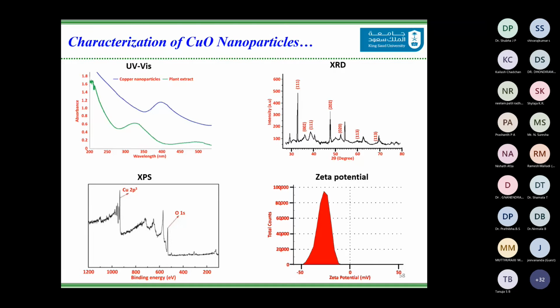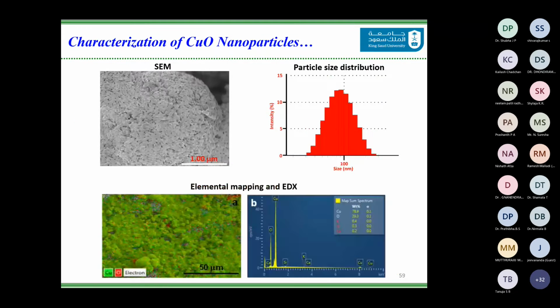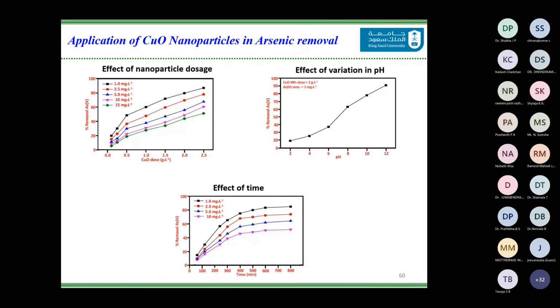The zeta potential analysis also revealed the dispersion of the nanoparticles, and the average particle size that we obtained from this study was about 92.3 nanometers, which is much higher than anticipated. However, these nanoparticles were used for the removal of arsenic from wastewater.